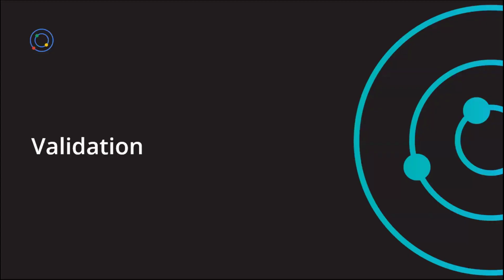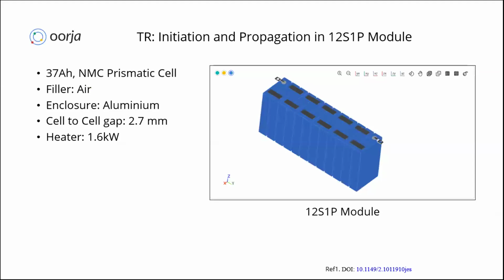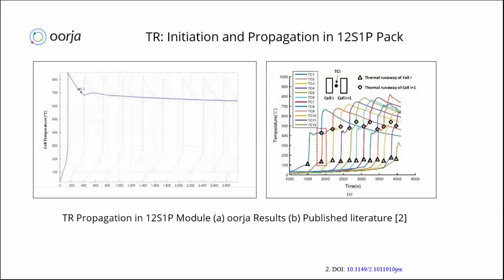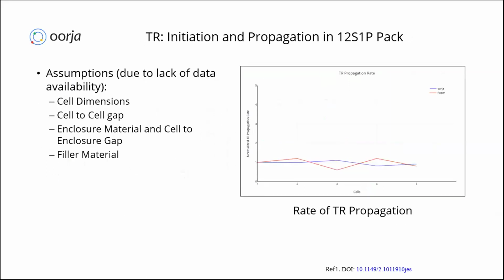So Urja supports these thermal runaway initiation and propagation models not just for cylindrical cells but other form factors as well, if you want to have pouch cells or prismatic cells also. One of such cases I am presenting over here is the prismatic module, that is the 12S1P module, which was done for the 37 ampere hour cell. Here we compared our Urja results with the published experimental data, wherein we could get a qualitative match with the published literature, wherein all the cells go into thermal runaway, and even the thermal runaway propagation rate could be measured. When I mention a qualitative match, it is because the design details were not available in that paper, and hence we could do only the qualitative match over here.